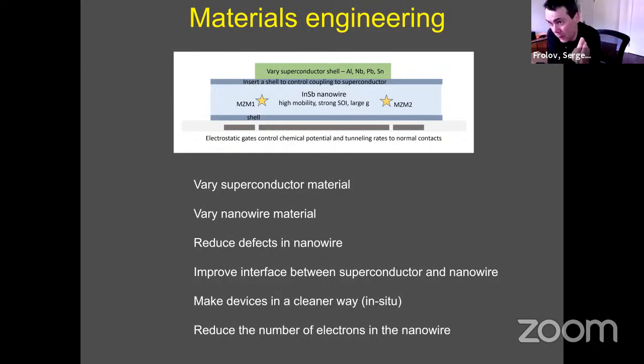Superconductivity is actually not sensitive to disorder. That's a beautiful thing about superconductors. There is an Anderson theorem, it's called, which says that disorder doesn't kill, but magnetic impurities do. Now, we don't have magnetic impurities, but our superconductivity is unusual. It's a P wave. It's a triplet superconductivity. And triplet superconductivity is sensitive to any disorder, also non-magnetic. So any disorder is bad. And so that's a motivation for why we need, the better the sample, the clearer the signal.